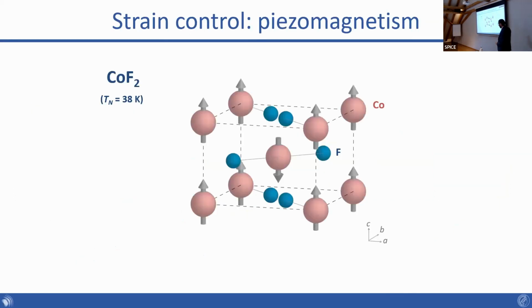Okay, so the model system that we use to do that is a very simple antiferromagnet, which I think hasn't been discussed so far, cobalt fluoride, but it's a very old antiferromagnet that's been studied since the 50s, really. It has a Néel temperature of 38 Kelvin, and it has a rutile crystal structure, formed of a BCC lattice of cobalt ions that you can see here. Each cobalt is surrounded by 6 fluorine ions, an octahedron of 6 fluorine ions. Now, in the antiferromagnetic state, the cobalt in the center of this cube has a magnetic moment equal in magnitude and opposite in direction to the one in the corner. So it's really a fully compensated C-axis antiferromagnet.